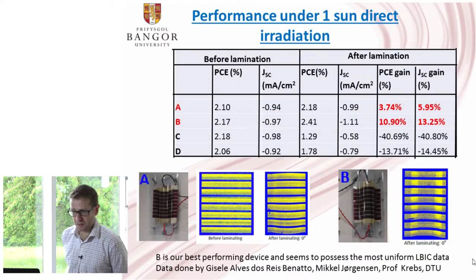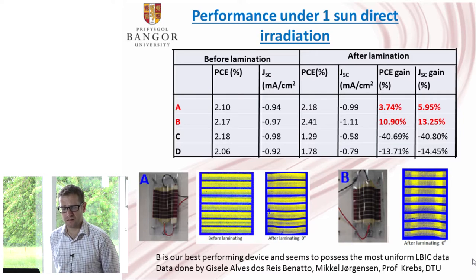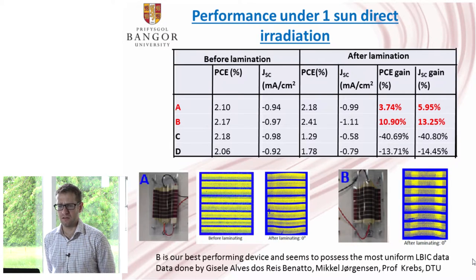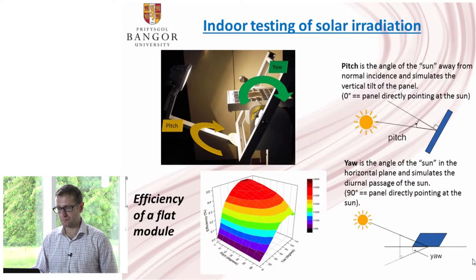We've done a number of studies looking at the performance of these solar cells under direct irradiation. What we find is that one or two configurations in particular work well when we laminate them onto these three-dimensional substrates. Typically the best performing module gives us about a 10% increase in solar cell efficiency, and that's using what we call our module B configuration. That's under direct illumination.